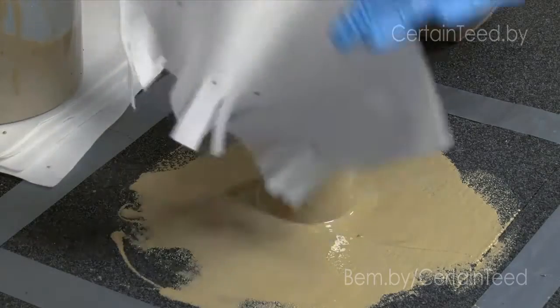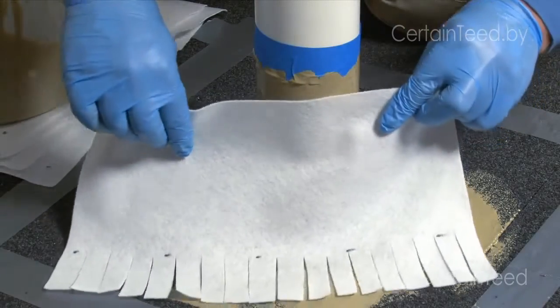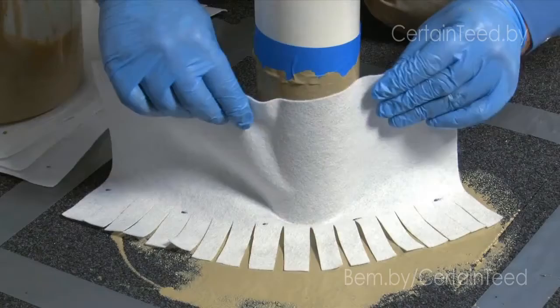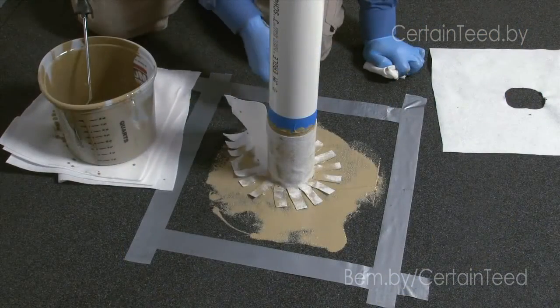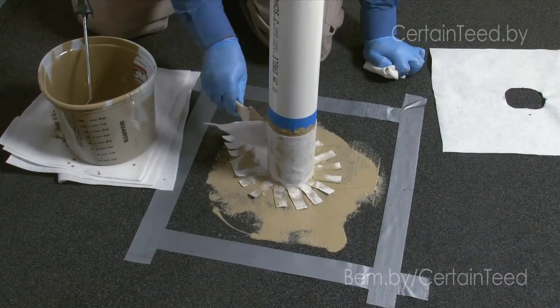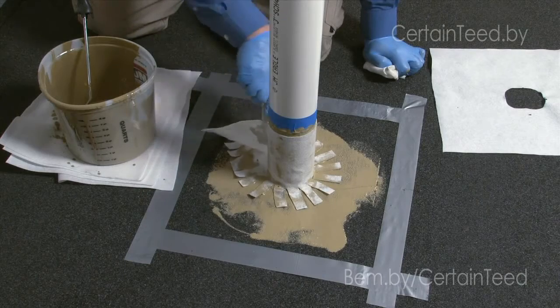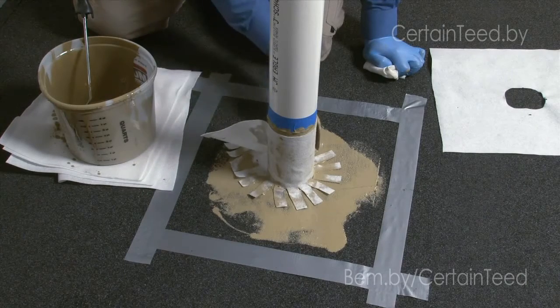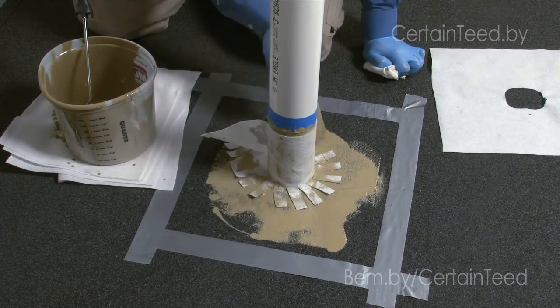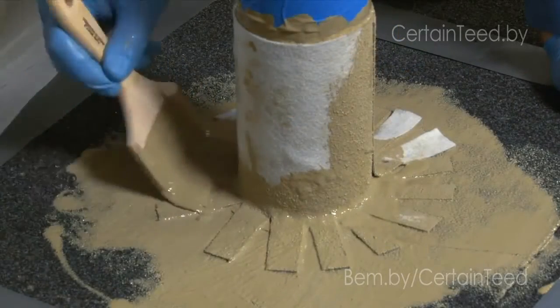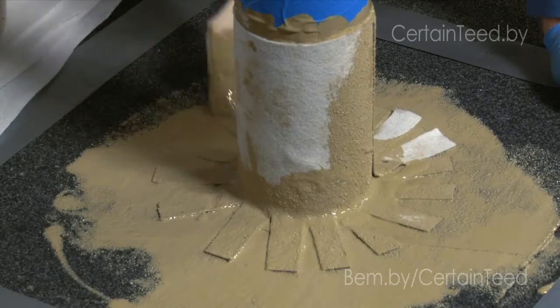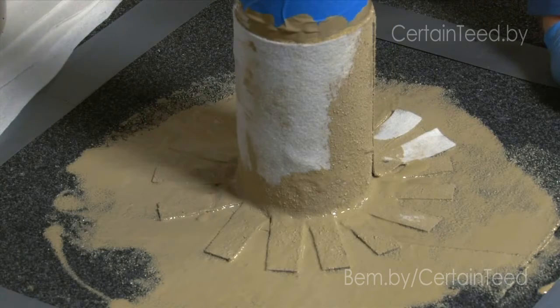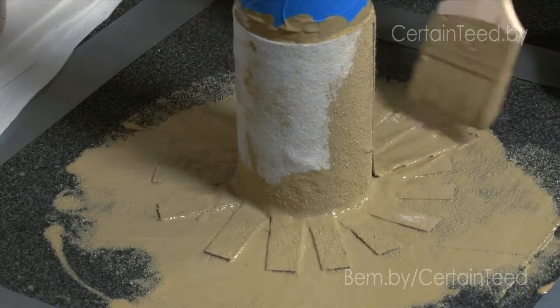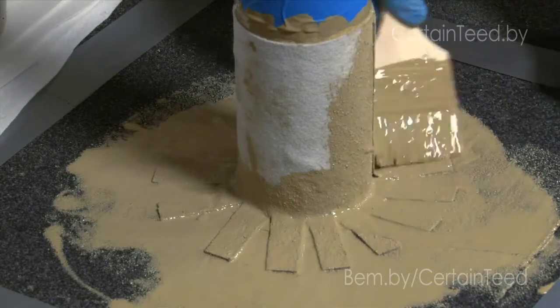Wrap the pre-cut fleece around the pipe, smooth side facing up. Using a roller or brush, work the resin into the fleece, saturating from the bottom up. The appearance of the fleece should be light opaque amber with no white spots. White spots may indicate that there is not enough resin used below the fleece, which, if not addressed immediately, can cause a lack of adhesion of the finished membrane.